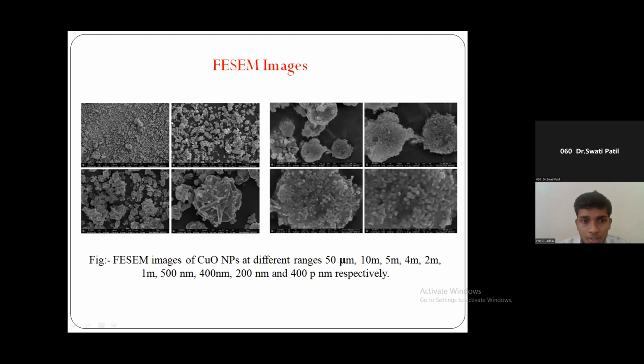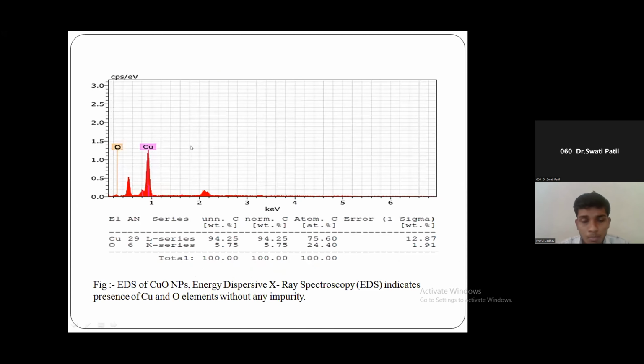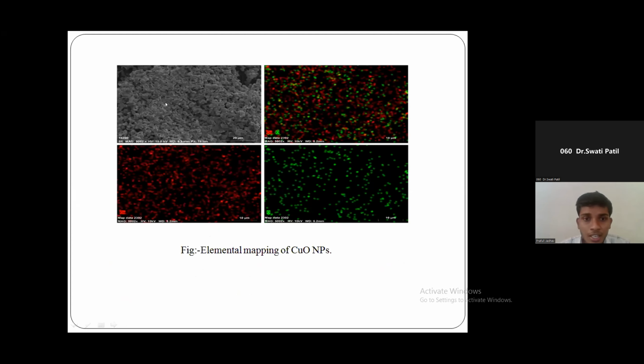These are the FESEM images which I have got at different ranges, like at 50 micrometer, 10 micrometer, 5 micrometer, then 4 micrometer. This is about 5 nanometer, and so on. Then this is the energy dispersive X-ray spectroscopy, that is the EDS plot. This indicates the presence of two elements, that is copper and oxygen, without any impurity. Then this is the elemental mapping of copper oxide nanoparticles.